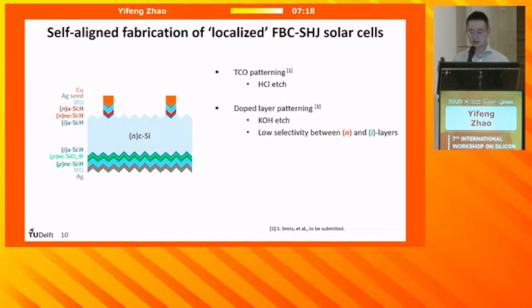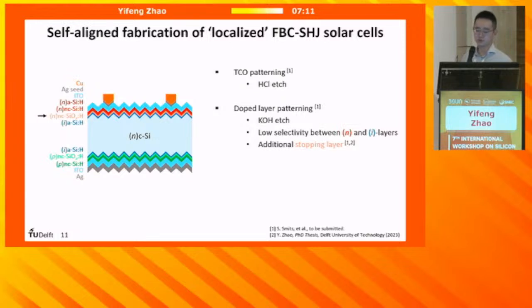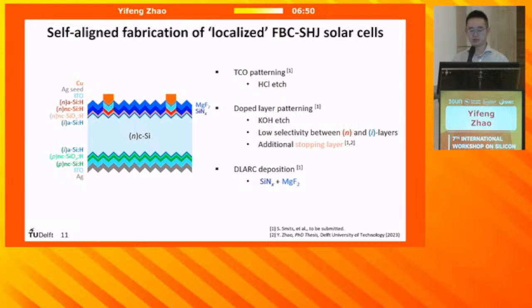So it is, of course, desirable to keep the intrinsic amorphous silicon layer untouched. So for this purpose, we introduced an additional stopping layer, that is N-type nanocrystalline silicon oxide layer, which was proven to be etching resistant and also efficient to act as a part of the electron transport layer. So with this layer, we can etch TCO, we can etch the N-type amorphous silicon and nanocrystalline silicon layer, and we stop here, and we deposit further silicon nitride and MgF2 layers for the light management.